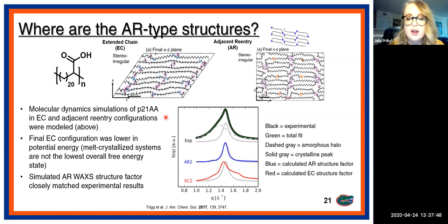So after this work, it was pretty much confirmed that the true morphology of the P21AA polymer is really an adjacent reentry type of secondary structure. So this has really exciting implications, because you can imagine how now you have these channels that are enriched with, if you can get them into this conformation, whatever functionality you desire.